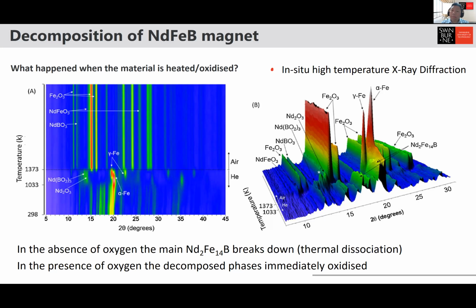Right? But if we heat it up in air, then immediately we also started to form NdFeO3. Right? This can be seen in this graph here. So the one on the top here from 1373 is when we switch the XRD from helium to air, we started immediately to form that oxide in there.